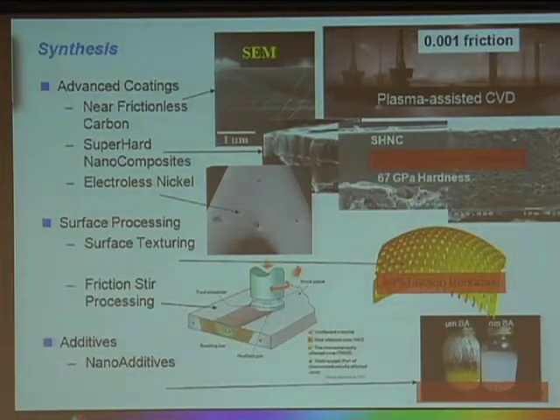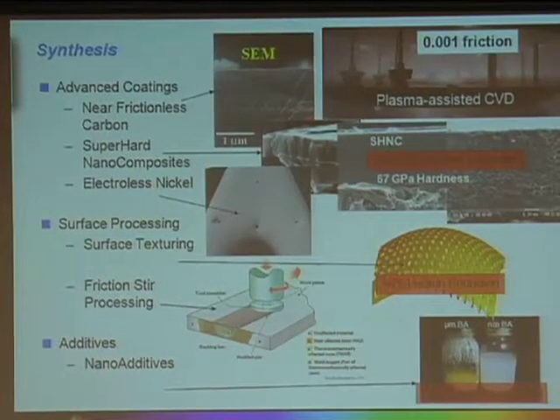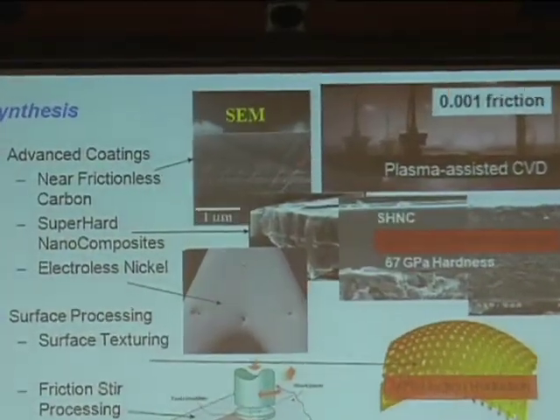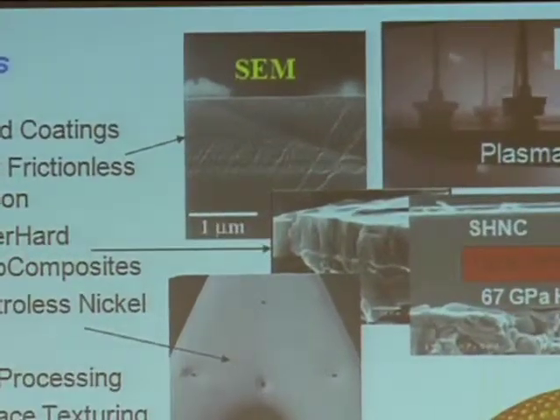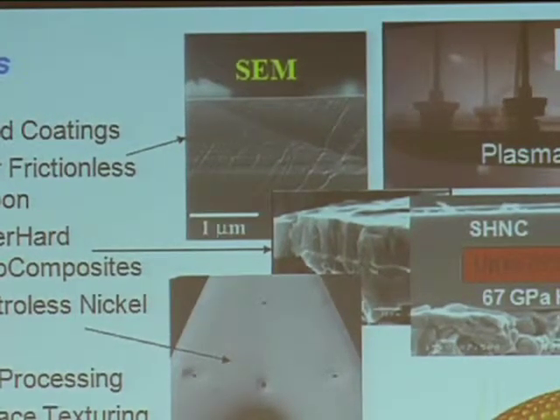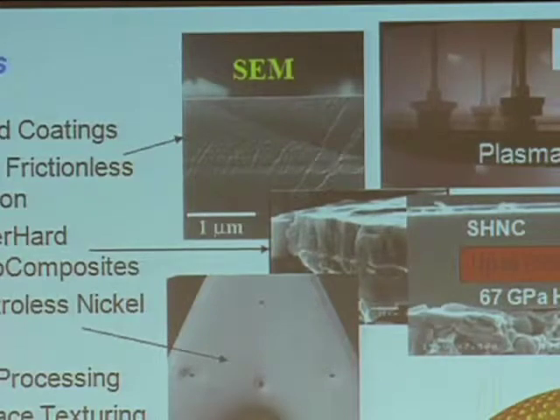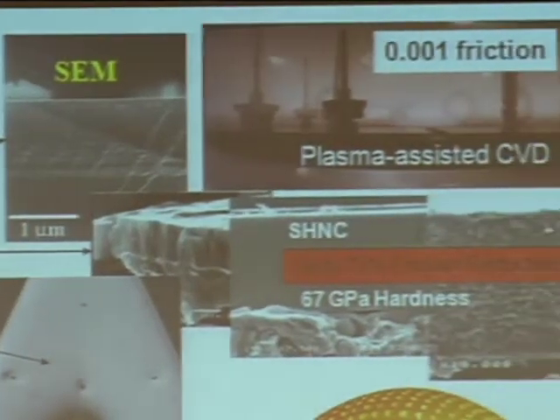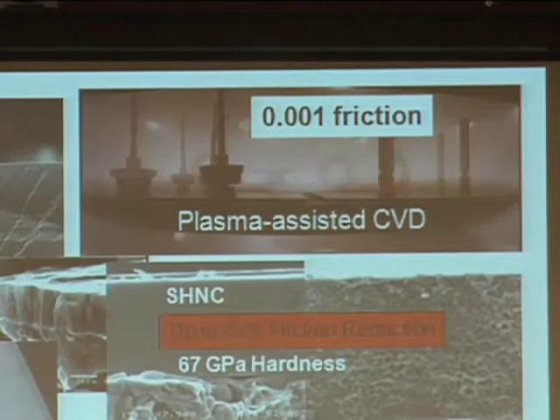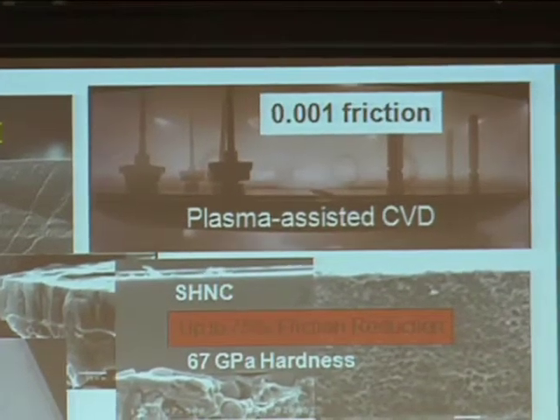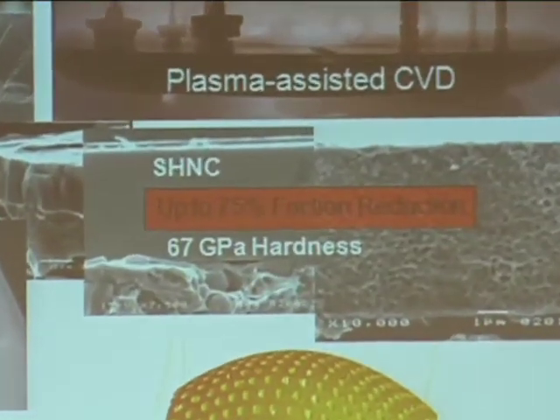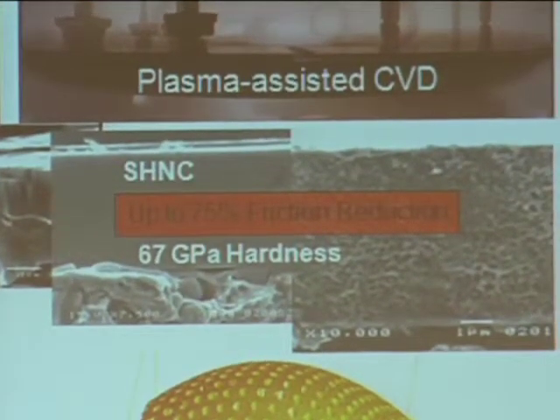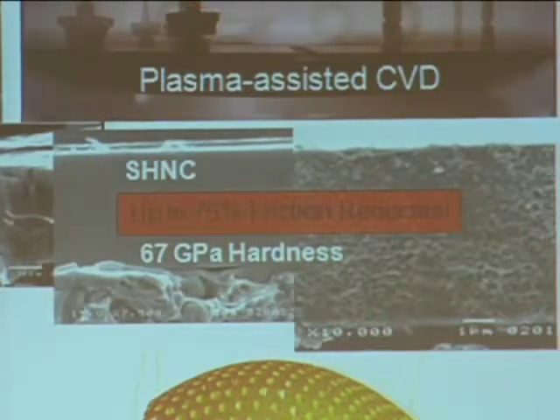In terms of some examples of the synthesis that Argonne is known for, in the area of diamond-like carbon, near frictionless carbon coatings, we've been working on this for a number of years. This particular form of diamond-like carbon coating has really set a world's record, with friction coefficients down as low as 0.001. To put that in context, if you were to slide steel against steel, you'd have a friction coefficient of around 1. If you can obtain a dry sliding friction coefficient around 0.1, most people are quite happy with that. We're as much as two orders of magnitude lower than that. So we have very, very good friction properties on that.